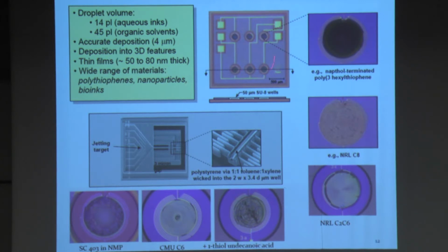This is our device here. This is jetted polythiophene. Actually, this whole project started with polythiophene. We jetted quite many of them and then discovered that they are probably good for OFETs, but they're not good for sensors because they drift. So we switched to the nanoparticles.